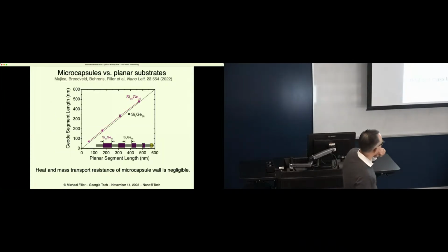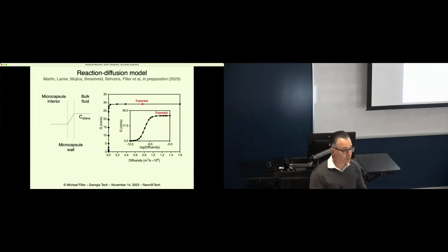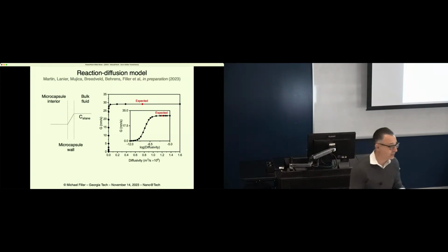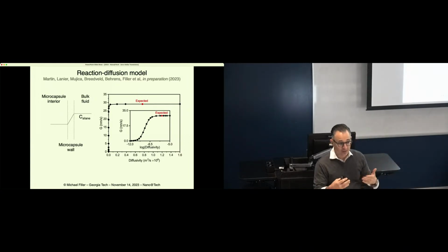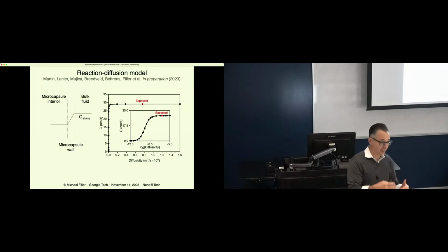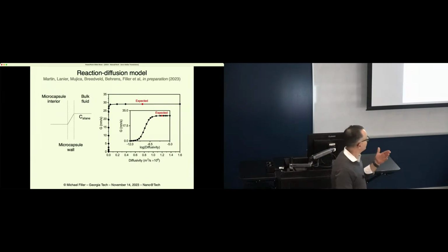And this is what I said a minute ago. If you were to put a substrate next to the geodes without any geodes and look at wires grown on it versus wires grown in geodes, and then plot the length of the segments for the ones in geodes against the length of the segments for the wires not in geodes, there's really no difference. And why is that? It turns out transport through the shell is really fast relative to growth. Okay, so if you're that wire, you're getting plenty of material to go into that droplet and nucleate the next layer of the growing wire in the time scale it takes to nucleate. Okay, so it's not an issue.